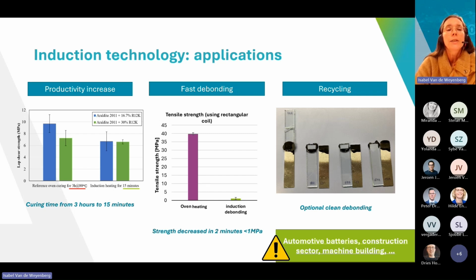On the left-hand side, you see a standard oven curing. So the parts need to be cured in an oven for 3 hours at 80 degrees, and you can achieve a similar strength with only 15 minutes under induction heating. So you can increase your speed from 3 hours to 15 minutes.